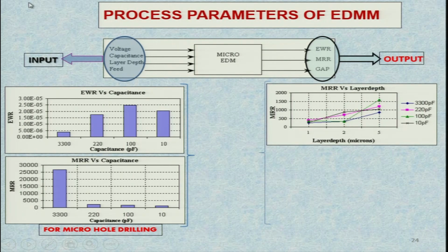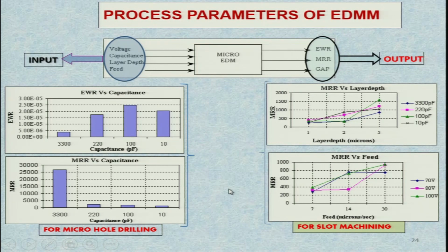Now, here you can see layer depth is in terms of microns, and here is the material removal rate. So, you can see for different picofarads as the capacitance, the performance of the EDMM process is different. And then for slot machining, again you have different voltages. As the voltage is increasing up to say 100 volts, you are getting higher material removal rate, but somehow at 80 volts the material removal rate is lower at certain feed rate, and then it starts increasing.